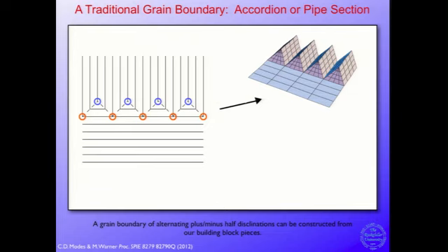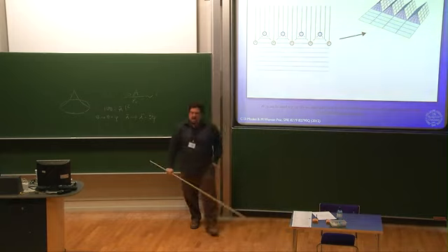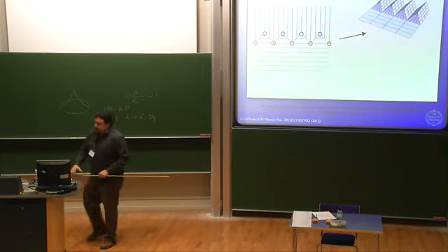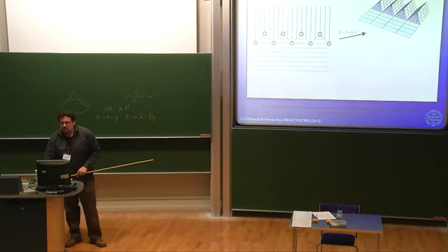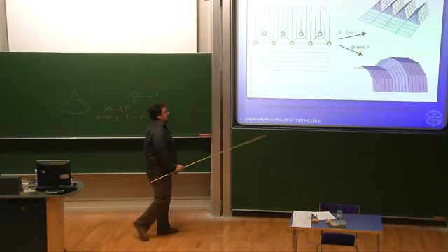You get crumpling, right? Because ultimately you want elongation along here and contraction along here. And so the way for the system to do it to first order is just to crumple the part that wants to get longer, and the part that wants to get shorter can just stay flat. And the presence of the curvature defects actually gives you exactly the right polygonal corners in exactly the right places to make this happen. As you increase the strain, however, and again, the bending energy, of course, now there's another place where the bending energy enters.